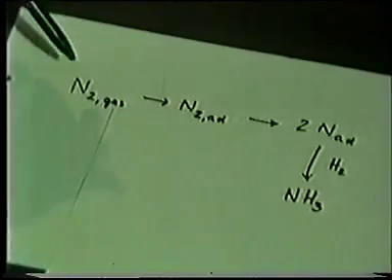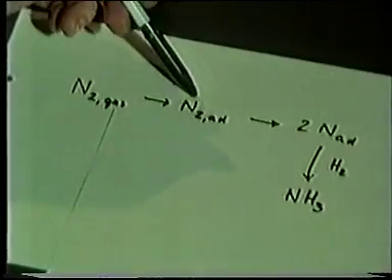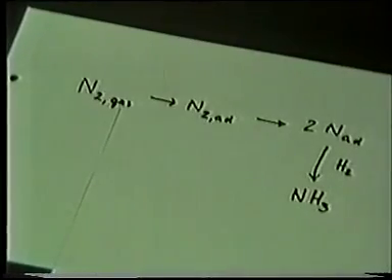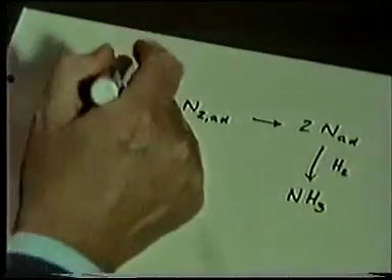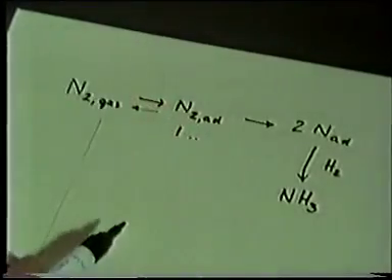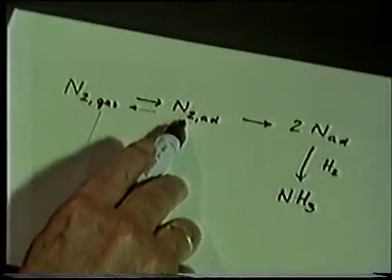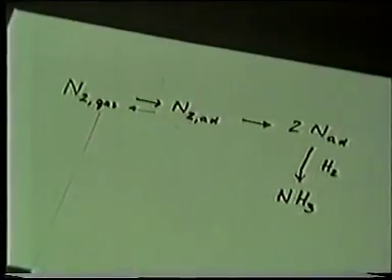Now if we look into this reaction in more detail, it turns out that it is composed of two steps: the formation of the molecularly adsorbed species and the dissociation of the latter. Independent studies revealed that the second step, namely the dissociation of the nitrogen molecule, is slower than this step here, the adsorption of the molecular species. And also desorption of the molecular species is a rapid process, so that we have in fact a pre-equilibrium from where the reaction goes on. So the dissociative adsorption of nitrogen is a rate limiting step for the overall reaction.